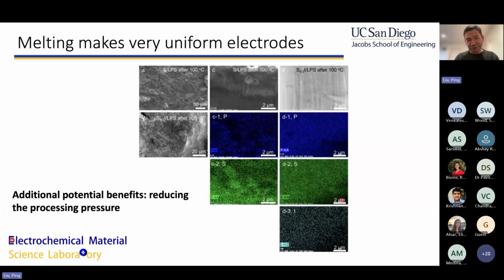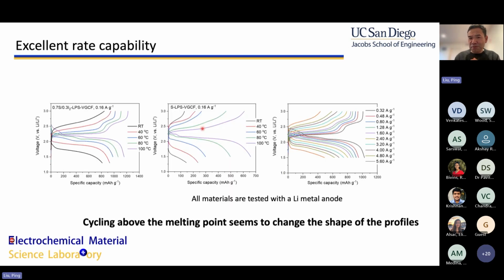And here's the proof. When we make a solid state material, usually we mix a lot of powders together: the active material, the carbon, the solid electrolyte. Now we have one material that we can melt. So that's why we make an electrode that's far more uniform than just sulfur itself. This is intuitive because one of them can melt, they can flow everywhere. And then the electrochemical performance is amazingly good.